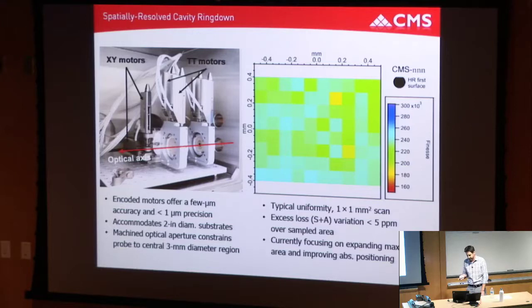One very nice thing about the single crystal semiconductor systems is the refractive indices are effectively fixed by nature. They don't vary from run to run like with a sputtering process, so we know our indices. We can do X-ray measurements of the film thickness. We can measure the superlattice, fit the peaks. We know our transmission. We can now measure the absorption by PCI. And then the ring down is everything. It samples transmission, scatter, and absorption. So we're just left with scatter as the one unknown. So we can map out scatter. We can scan the PCI system for absorption. We can do very, very high-level characterization of the optics. And this is what it takes to get to these levels of performance quickly, and catch up with IBS instead of waiting a couple decades.